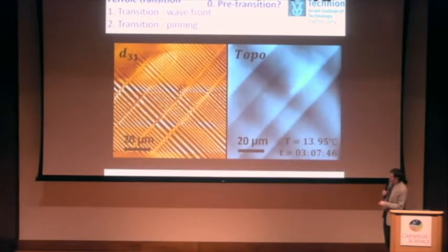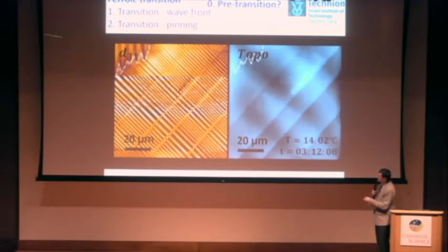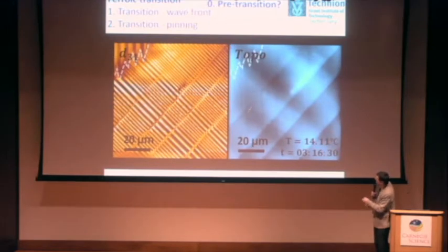So what you see here is the same video that you saw before, but just of the transition. And here you can see these kinds of lines in the topography. You see one line here, and then two here, and then another two here. So it goes in a kind of periodic structure. And you see, as the phase comes in, you lose them one by one.